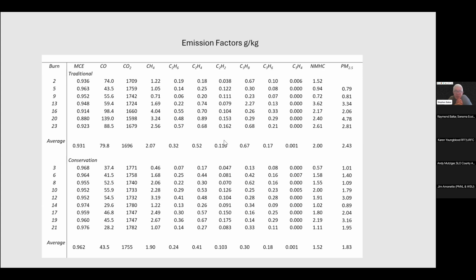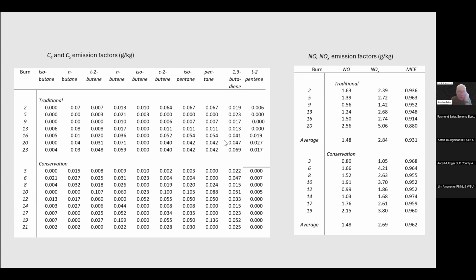And the PM 2.5 emission factors, which were based on those filter samples that we took, you see 1.83, quite a bit lower than 2.43 for the traditional burns. And then looking at some of the other emission factors here for C4 and C5 compounds, you can see that those were all pretty low in both cases.